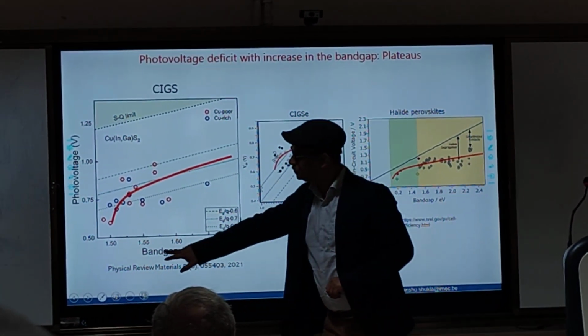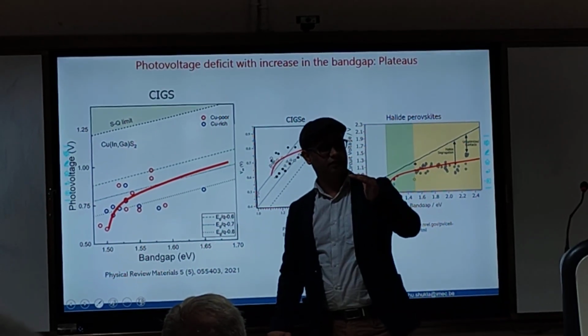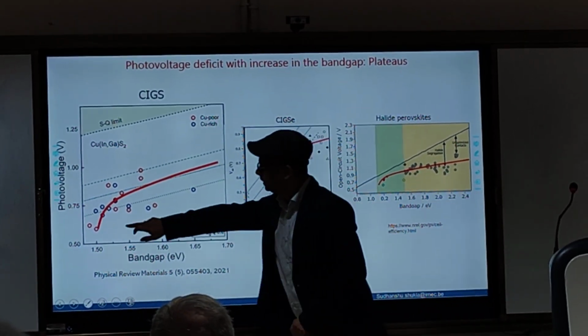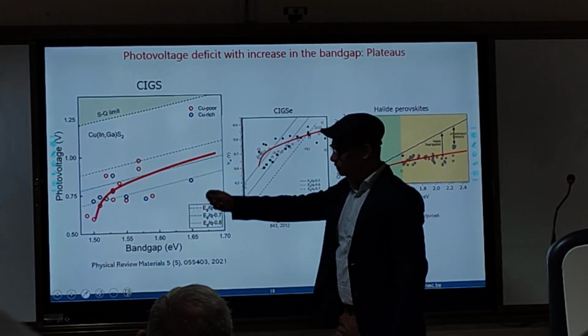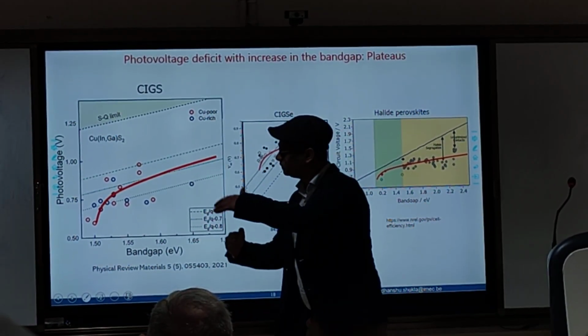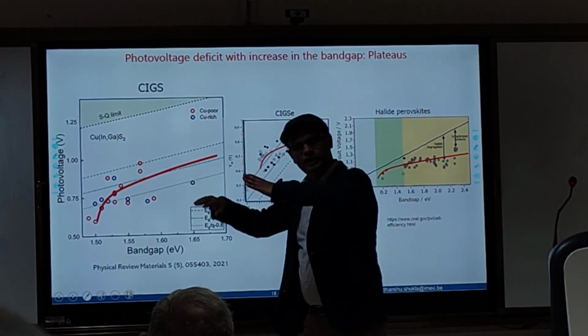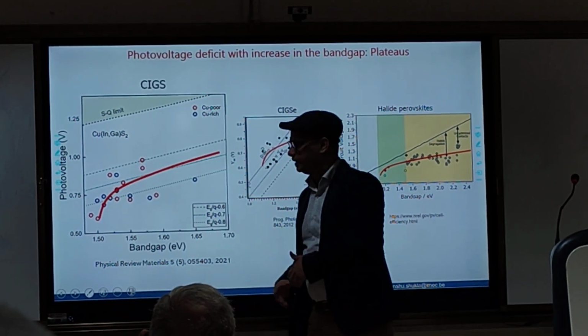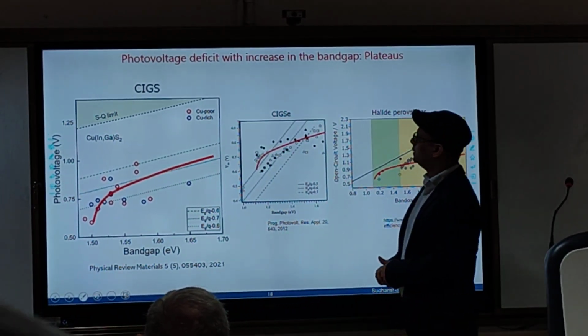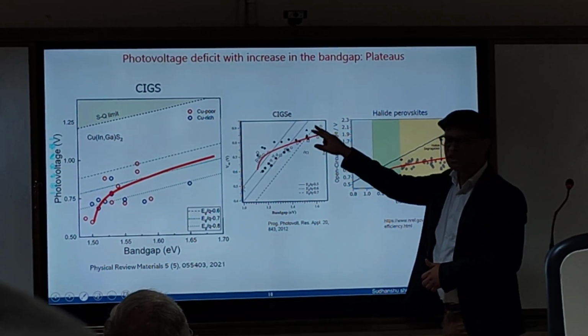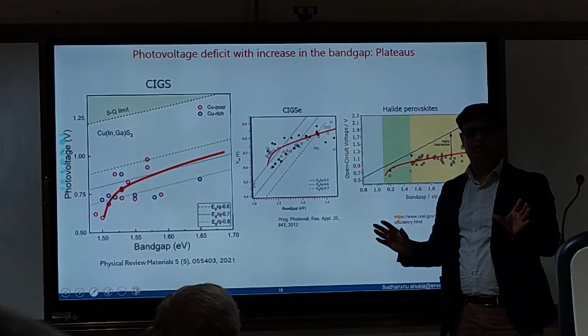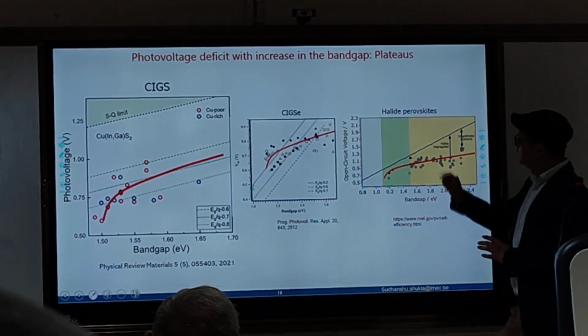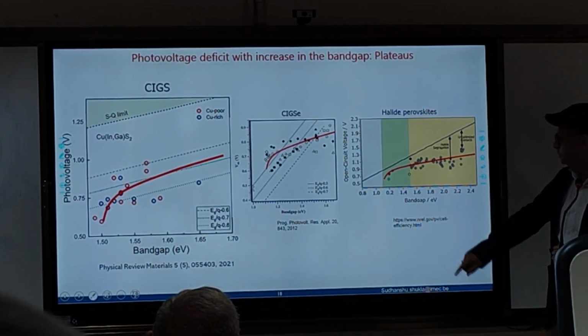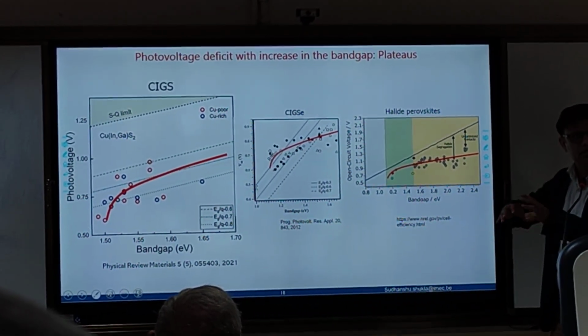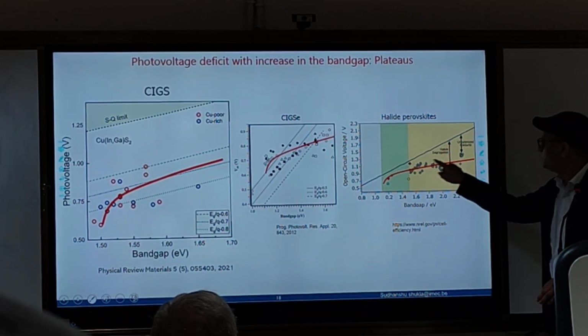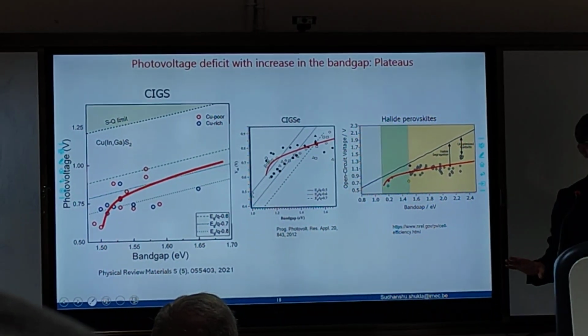When you increase the band gap, and I told you the photovoltage should scale with the band gap, so it should increase, but it actually plateaus. So you see, when you expect your band gap to increase, the photovoltage to increase in a linear fashion, or at least, let's say, more or less should follow the band gap. But you see this plateau. You also see this plateau in this CIGSe material, which is the state-of-the-art material from thin film. You see this plateau is coming. Even in halide perovskites, which are very good, try to increase the band gap by alloying or something, you still get this plateau. So something very fundamental happens.